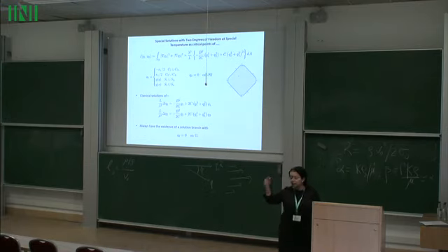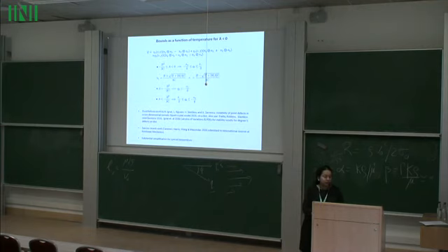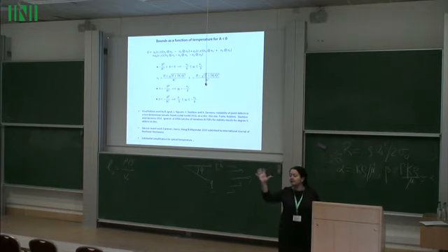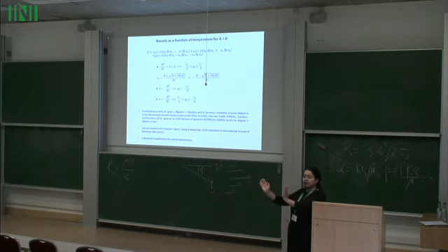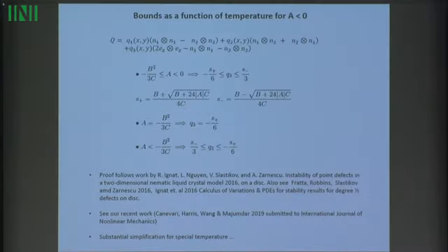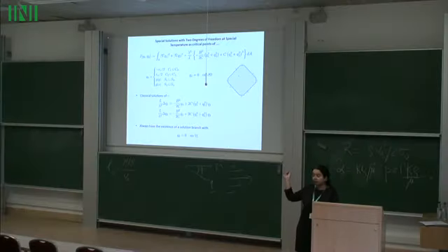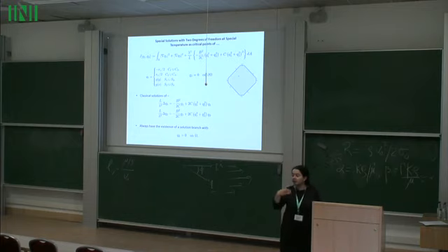But I think what Professor Mike Cates is saying is that there is a 3D interpretation, because all of this was done at a fixed temperature where Q3 is constant. So there is actually a third component; it is still 5 degrees of freedom, but this Q3 bit is separated because it's just a constant. And from the numerical point of view, you just looked at this problem, which has 2 degrees of freedom, Q1 and Q2, on a square, and looked at its critical points.